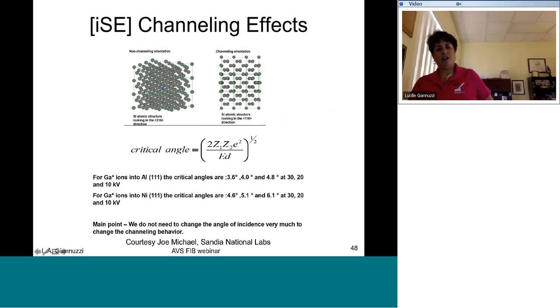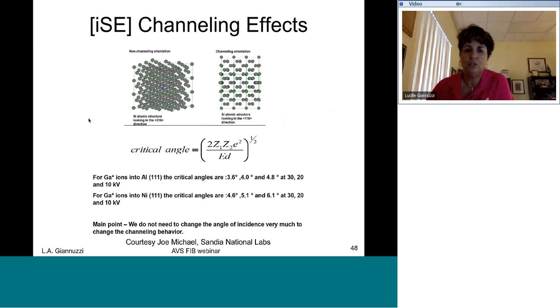Okay, here's the channeling effects. Now we're getting into an area where the material itself can very much affect what's going on. In particular, it can affect both the contrast as well as the sputter yield. So if we look at the critical angle for channeling, it has this sort of an equation. So for gallium ions into aluminum 111, the critical angles are 3.6 degrees, 4.0 degrees, and 4.8 degrees at different energies, 30, 20, and 10. And for gallium ions into nickel, critical angles are 4.6, 5.1, and 6.1 degrees at 30, 20, and 10.